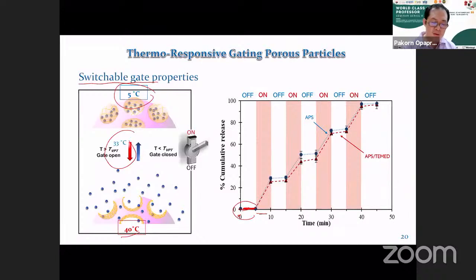you can see that in about 5 minutes, we see a release of the fluorescent dye to around 12 to 13%. After that, we cool this back to 5 degrees Celsius again. As a result, you can see the release stops, because we close the gate. Over 5 minutes from here to here, we do not see any increase in the fluorescent dye. But if we do the second cycle by increasing the temperature again, we see an increase of around 10 to 15% again. So you can see that we can do this for around 4 cycles. We can almost completely release the encapsulated fluorescent dye from the particles. So this shows very high potential for drug controlled release applications.